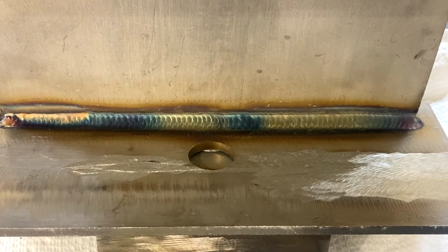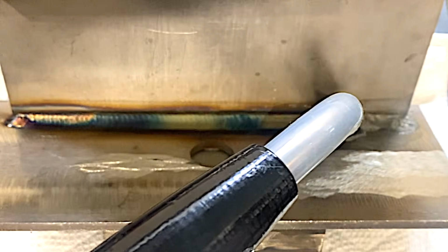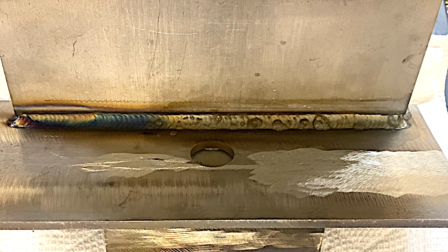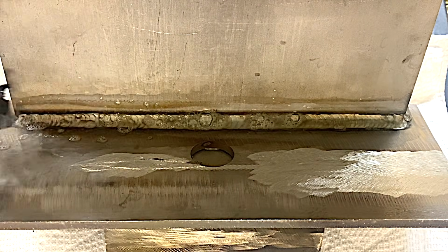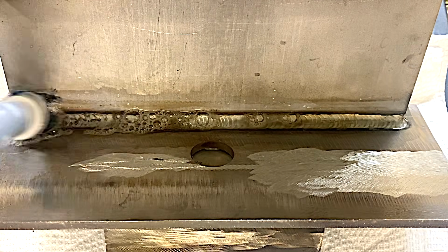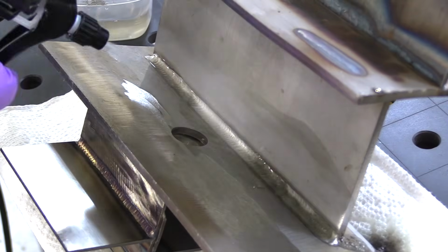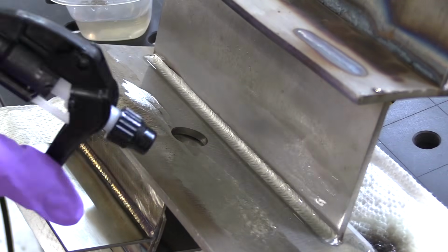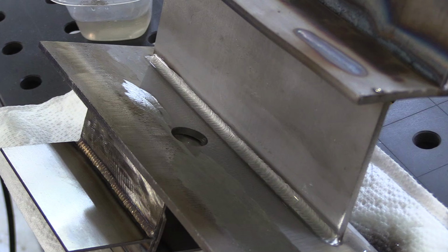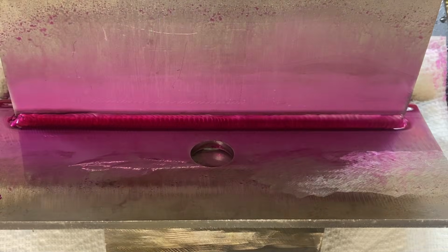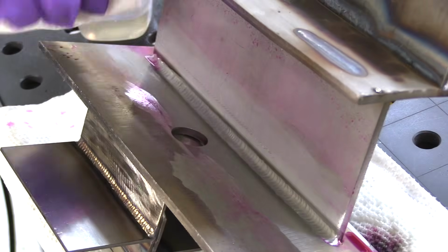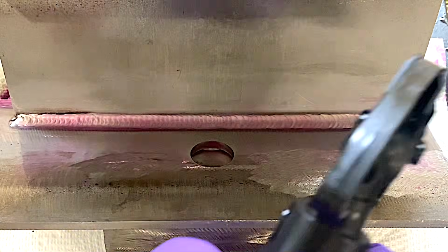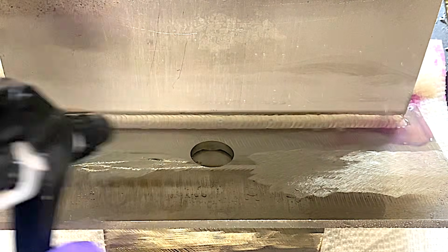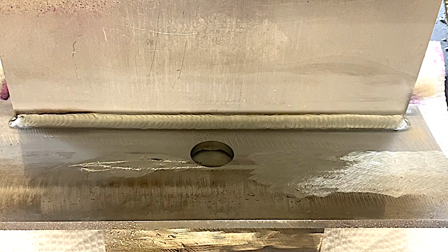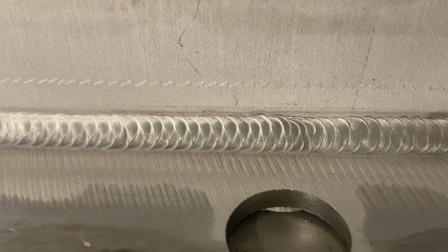So now let's remove that heat tint using the EK Plus. The brush is made of carbon fiber bristles. That way the electrical current can be passed through that solution and provide that cleaning action. After a quick rinse, we'll put the neutralizing solution on and leave that on there for a minute or so. A wipe down, another rinse. That is quite a difference. This weld will be much more corrosion resistant than with the heat tint on there.